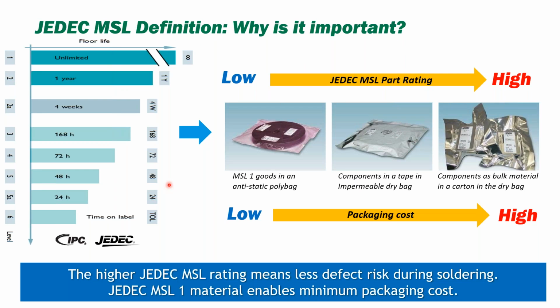The JEDEC MSL testing was designed to tell you how long you can leave the material in a room temperature and humidity environment, which I think they rate at 23°C and 50% relative humidity. But you can see that a level 1 part has, theoretically at least, an unlimited shelf life, whereas a level 2 can only sit for about a year in the open ambient air. So it's possible, depending on the conditions where the parts are made, if you're in a hot and humid area, it's much more likely it'll absorb moisture than a cool and dry area. But it's much more likely with a level 2 material, you will have to dry pack the parts than a level 1.